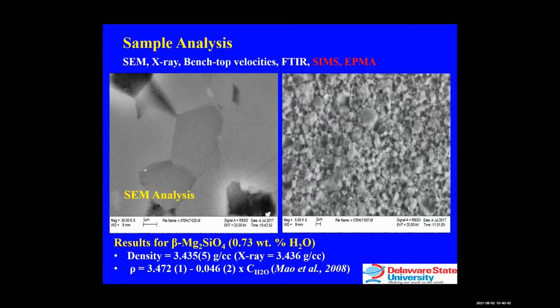fairly random. Fine grain is essential because the velocity measurements involve the propagation of high frequency, usually 20 to 70 megahertz, signals through the sample. So as shown at the bottom of the screen, the bulk density of the sample that we are talking about and the X-ray density based on the relationship here from Mao et al. agree excellently.